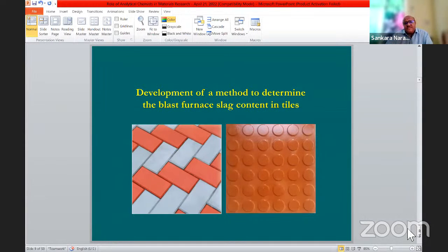The government is ready to give some subsidy to companies willing to use a large quantity of blast furnace slag. Generally, the construction industry can use a lot of these materials, fly ash and blast furnace slag. So they used this slag and developed the tiles. When they approached the government to claim the subsidy, the condition was that they must use at least 25% blast furnace slag in the finished tile.